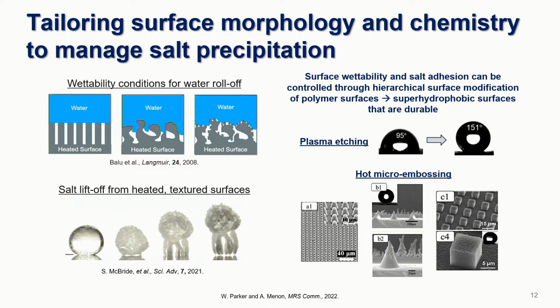lift off. And so we're doing some preliminary experiments with the micro-embossed surfaces, and we see that they're very stable under the salt environments and temperatures that we work at, and we're currently characterizing exactly how to optimize these surfaces in order to get very repeatable superhydrophobic behavior. So that would allow us to really control the movement of water and salt on different surfaces as we do desalination.